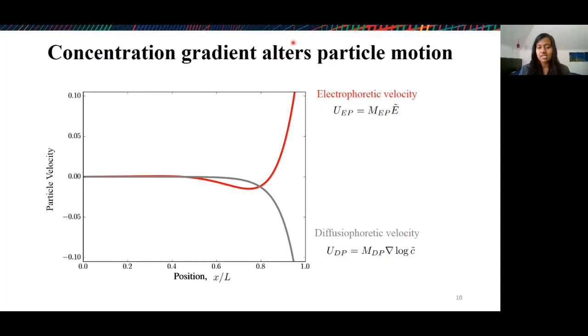So as you can see, especially closer to the electrode, the diffusiophoretic velocity and the electrophoretic velocity are comparable. And so the total velocity of the particle is actually quite different from just the electrophoretic velocity. And so we would have to consider particle motion under both electrophoresis and diffusiophoresis to really complete the picture of particle motion in these systems.